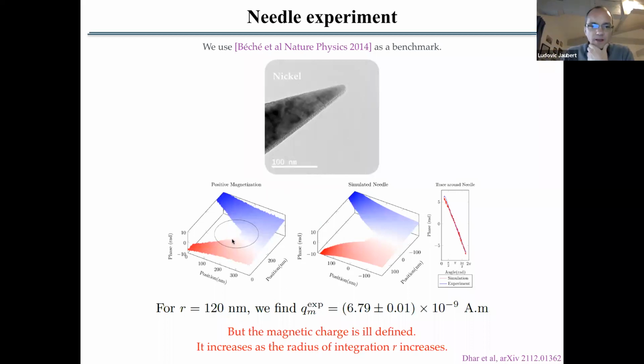And so here we have done the experiments, which is the left panel here, and compare it to simulations, which is the middle panel here. And you can see that experiments and simulations, once you take the proper value of density of magnetic moment and so on, match very well to each other. The white part here being the needle, okay? So that's where the needle comes in.